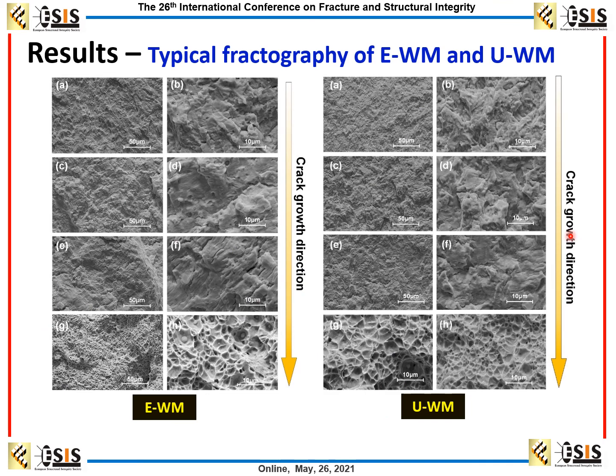The fracture morphologies of even matched and undermatched specimens under these regimes are shown at two different magnifications. The dimples on the fracture structure of even matched specimens are deeper than the undermatched weldment specimens, showing the typical ductile morphology for metallic materials. It further indicates that the even matched weldment has stronger plastic deformation ability than the undermatched weldment.